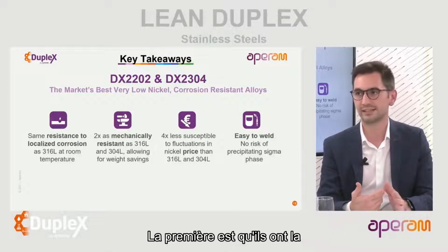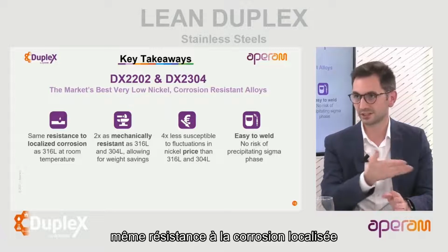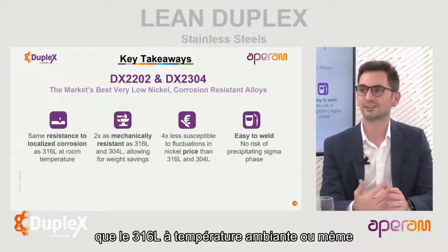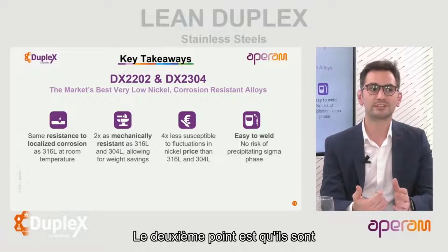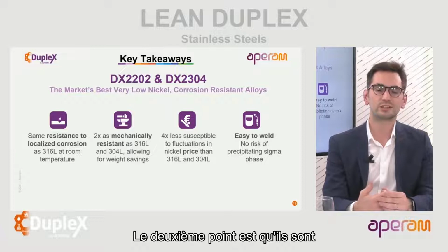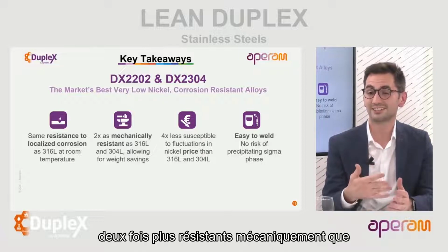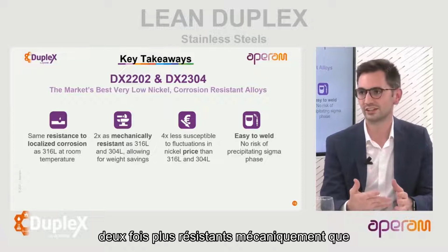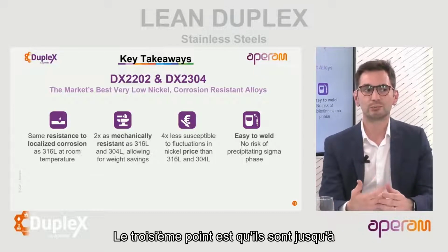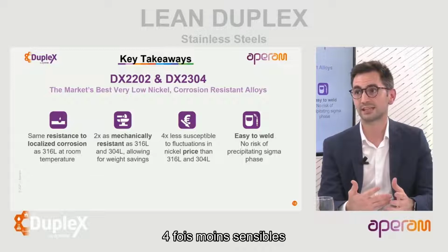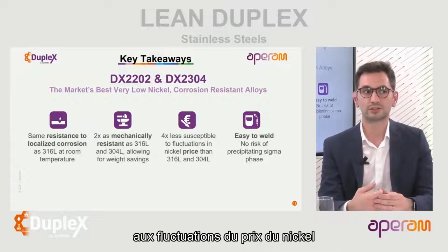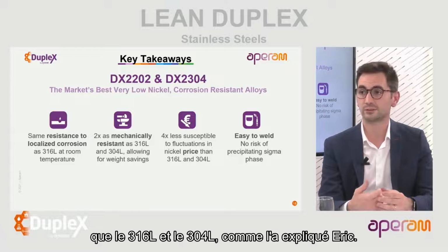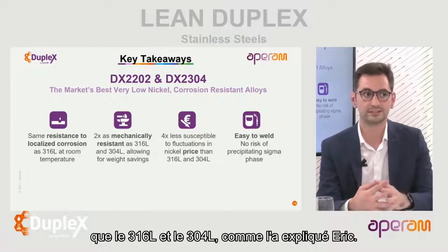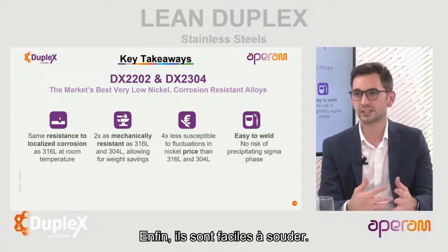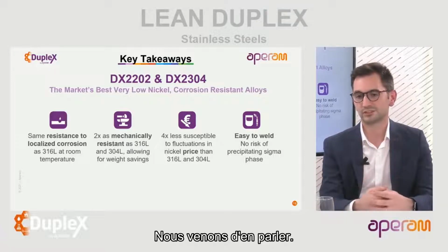The first one is that they have the same resistance to localized corrosion as 316L at room temperature, or even better. The second point is that they are twice stronger than the austenitic grades. The third point is that they are up to four times less susceptible to fluctuations in the nickel price than 316L and 304L, as Eric explained. And finally, they are easy to weld. We just talked about that.